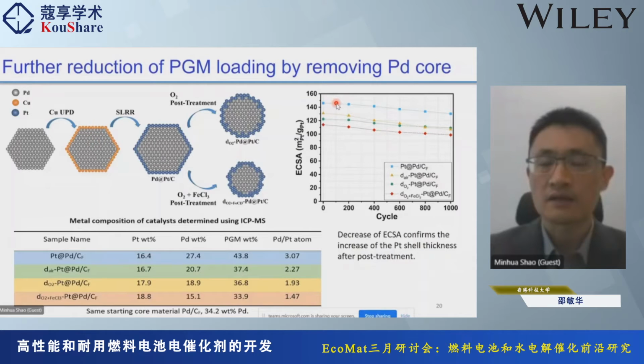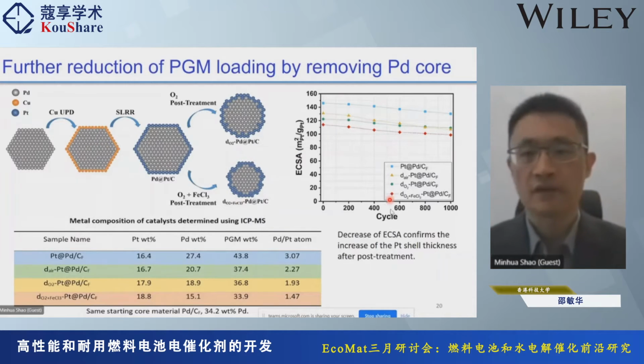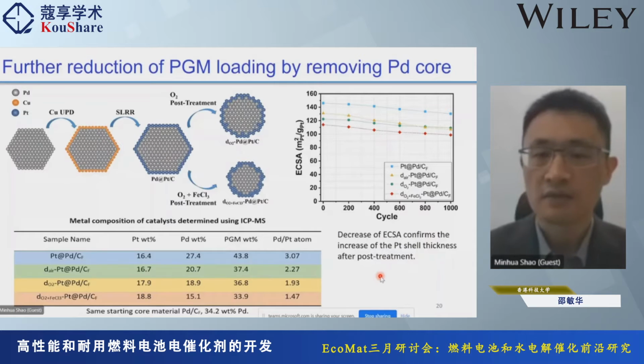Okay, and the surface active area comparison also confirms the increase of the platinum shell thickness. Okay, so initially we are talking about 150 square meters per gram of platinum. Okay, after post-treatment, for the last one, it decreased to about 110. So that means some of the platinum is actually buried in the sublayers, resulting in this surface area reduction.